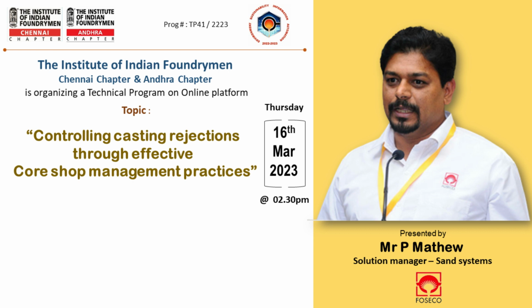Okay. For a molding sand, we need surface finish, because there are two aspects here. One is your molding sand AFS itself will be roughly 15 to 20 AFS higher than your core making sand. Second thing, fines are kept for a purpose, for the surface finish. Cores are coated to get your surface finish. But for the mold, there is no coating. What you get as surface finish is exactly from the molding sand fineness number. Okay, sir.